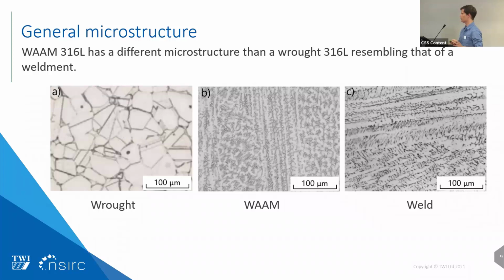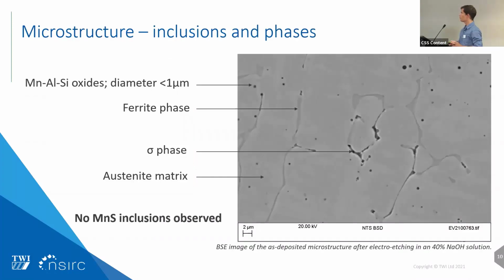If we look a bit closer at the microstructure now using SEM imaging, here you can see again an as-printed sample that has been electro-etched in a 40% sodium hydroxide solution. This etching is here to reveal the sigma phase that could be present in the material. As you can see, we have sigma phase present that is taking over the ferrite phase during the cooling stage, so we can notice the presence of these inclusions.